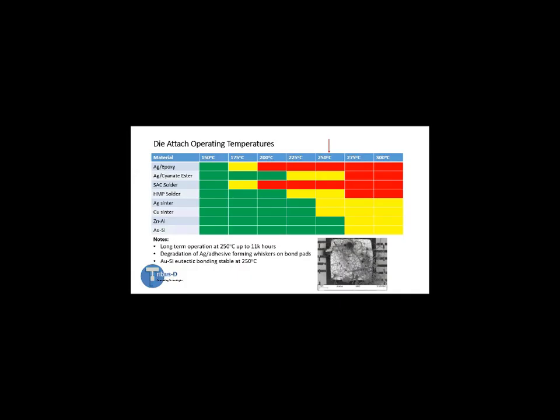We also saw at the time that most of the material suppliers are very comfortable in supplying data on materials and degradation, say for 1,000 hours. They'll give certain numbers of temperature cycles which a material can survive. But what we were looking for, particularly in the aerospace industry, was long-term performance. And we then started cooking things at 250 degrees C for up to about 11,000 hours, which was longer than the life of the oven which we were using to do it.